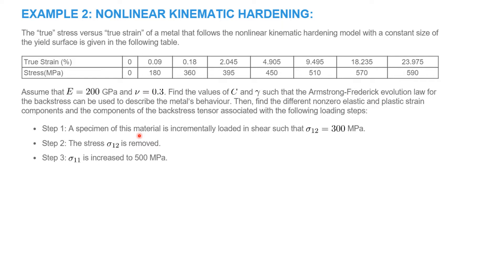First, it is required to find C and gamma such that the Armstrong-Frederick evolution law for the back stress can be used to describe the material's behavior. Then, the different components of the stress and strain are required to be calculated if loading is done in three steps: in the first step, a shearing stress of 300 MPa is applied; in the second step, the shear stress is removed; the third step is associated with an increase of sigma₁₁ from 0 to 500 MPa.